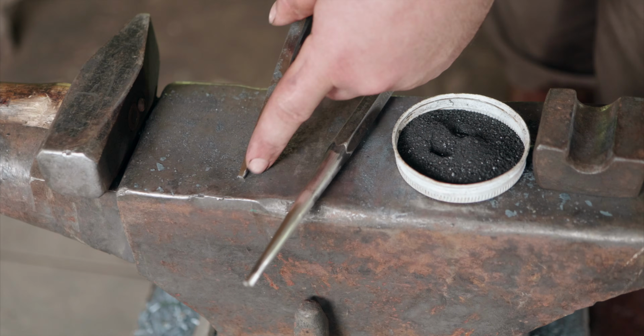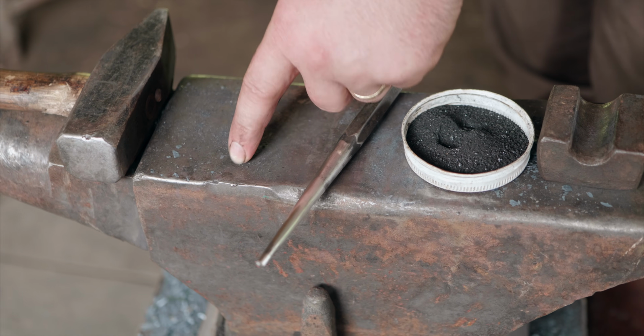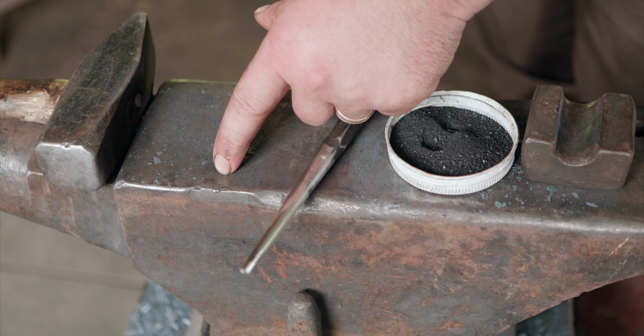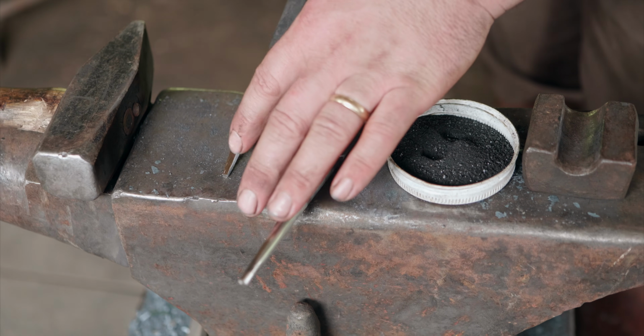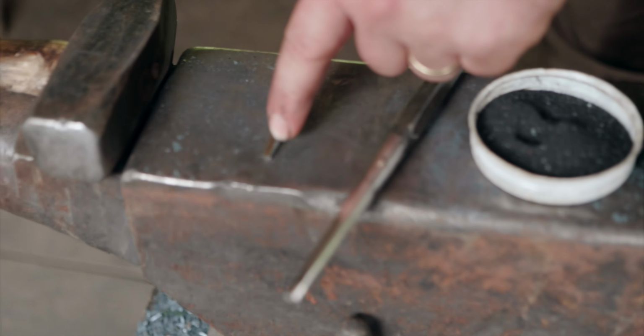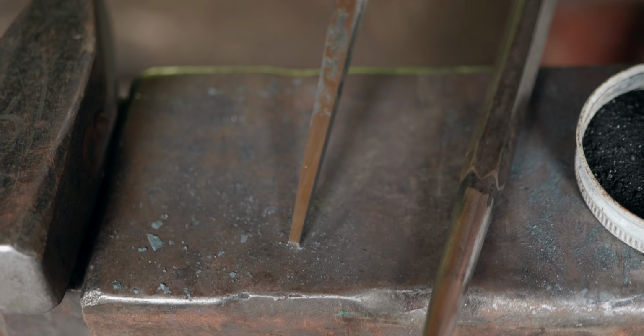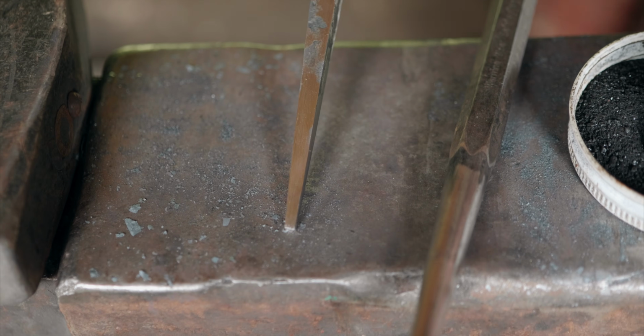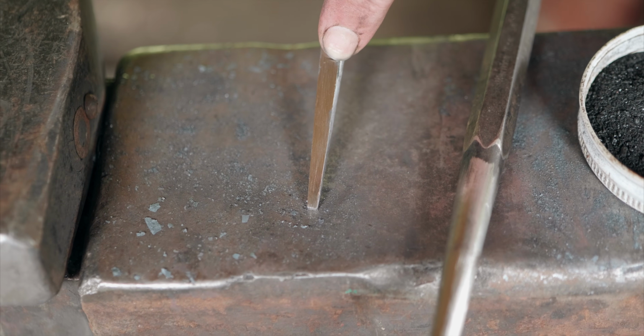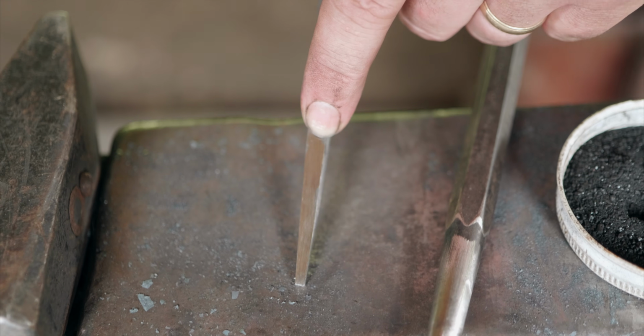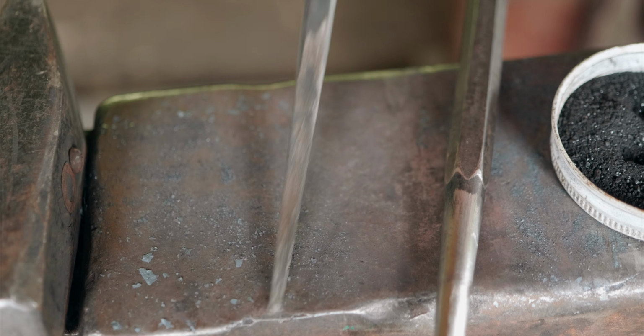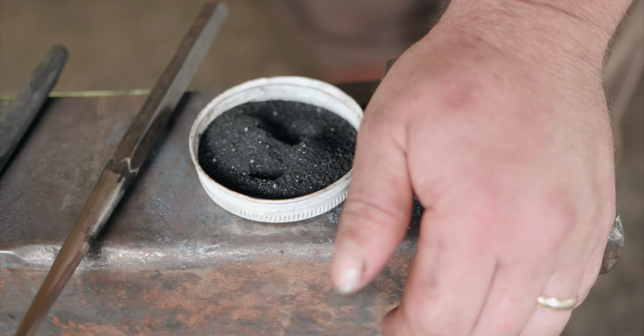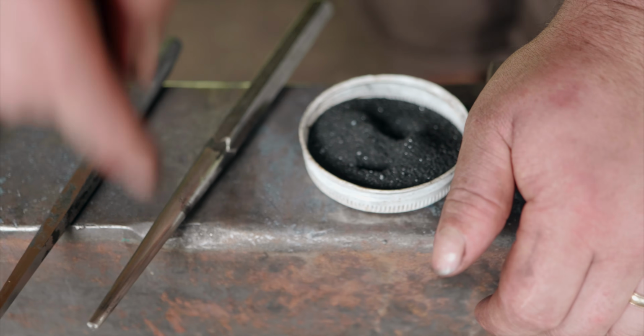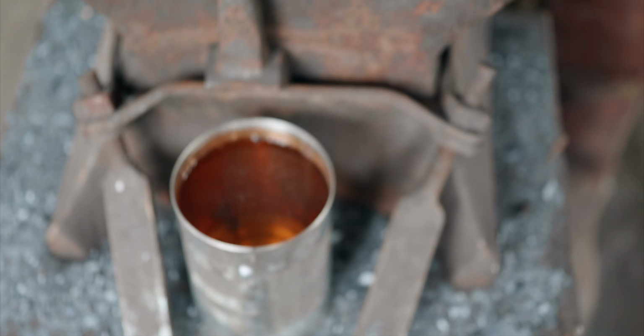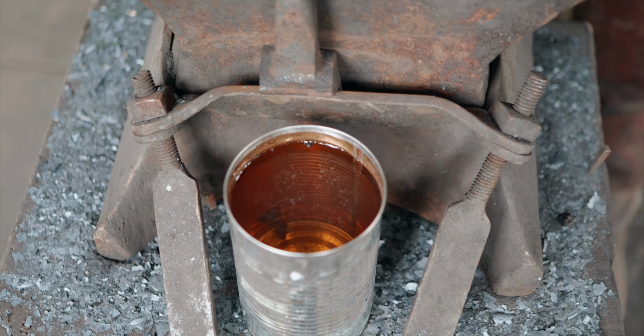Square punch has a fairly slim taper. It's 1/8 of an inch at the end because that's the size hole I want to wind up. Normally, as I said earlier, for a normal nail header, 3/16 would be my preferred size. And it tapers too. It's probably a 1/4 inch thick, maybe a little over, 2 inches up the shank. I've got a little dish of coal dust to help keep the punches from sticking, and I've got a water can to cool the punch.